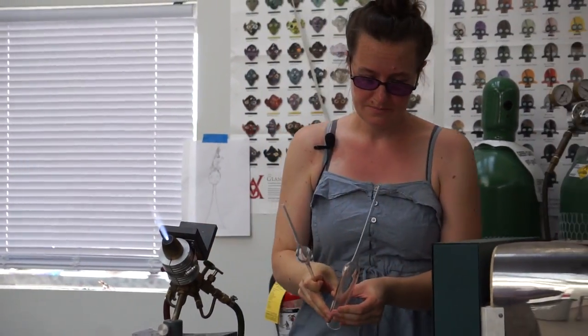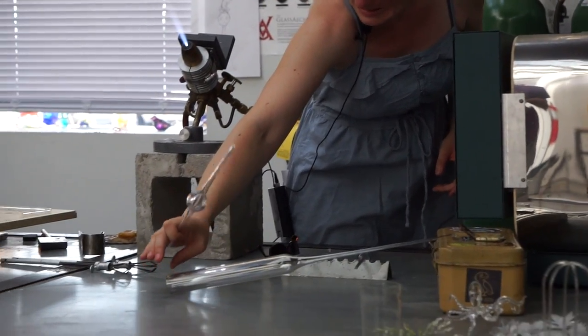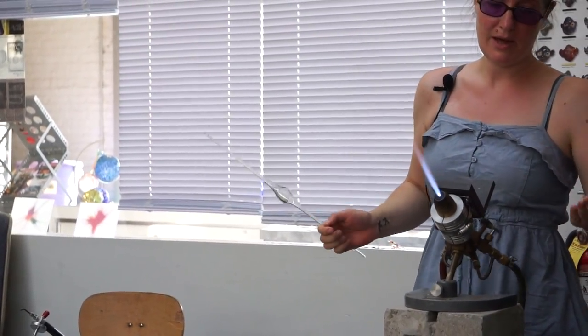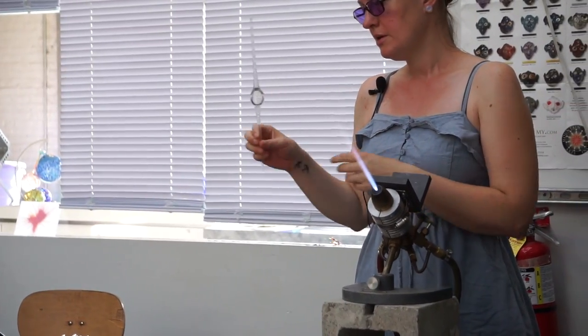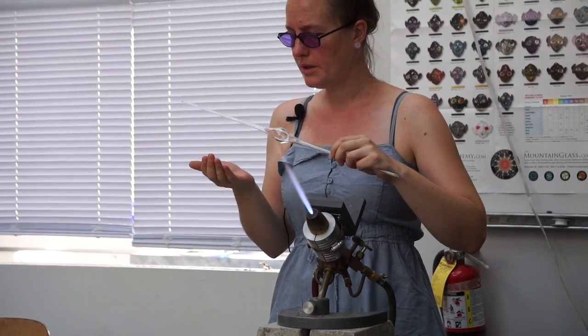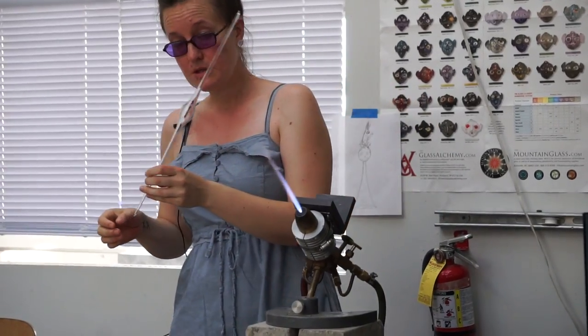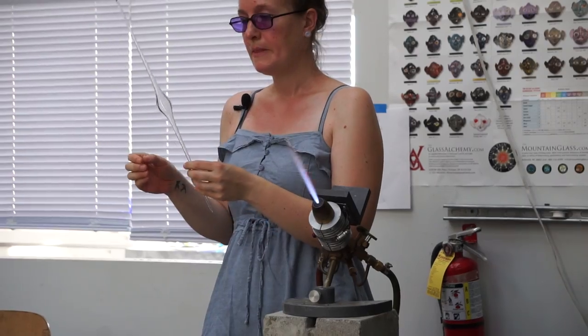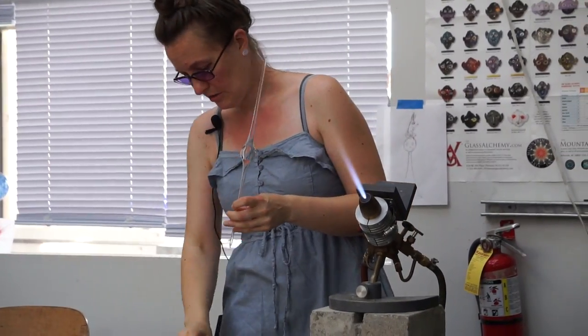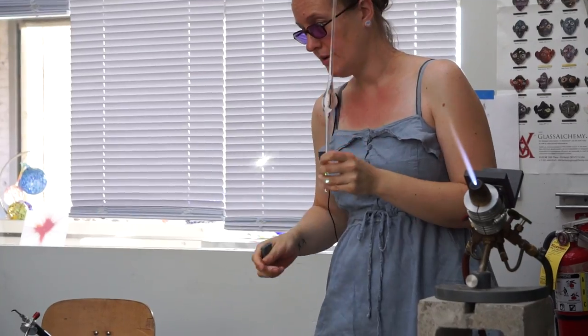Now I have a nice little bubble that I can make a foot out of. When glass is hot, if you put it on something cold and metal it'll crack, so I want to keep that hot part up off the table. This is my nice little pod now, and this part will cool off pretty quickly. If I try to heat this thing up while it's closed, the air inside will expand and a little bubble will shoot out the side. So I'm gonna open up this end — I scored it and then snapped it.